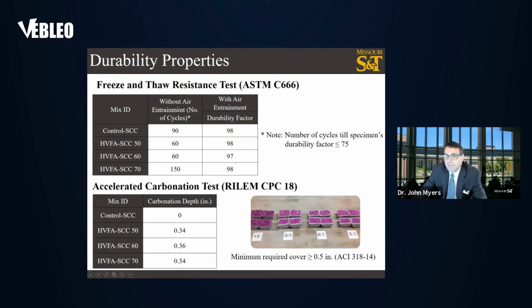Without air entrainment, it may be noted that the high volume fly ash with 70% also had outstanding performance in the freeze-thaw testing. In addition, the RILEM CPC-18 accelerated carbonation test was undertaken. This helps to ascertain the carbonation depth of the mix design. And here you can see the results of these.